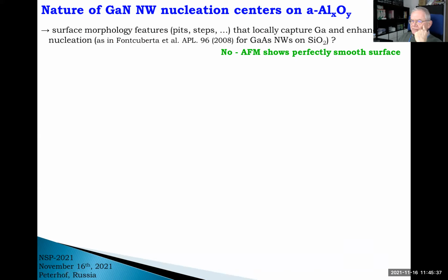Well, we spent a lot of time studying surface morphology using AFM, TEM, and all these available tools. And the point is, we do not see any surface morphology features such as pits or steps that might locally capture gallium and in this way enhance the nucleation rate of nanowires. This is a process well known for gallium arsenide nanowire growth on silicon dioxide, for instance, where there are pits in the silicon dioxide where gallium collects and a nanowire forms. We do not see any such features in our case.